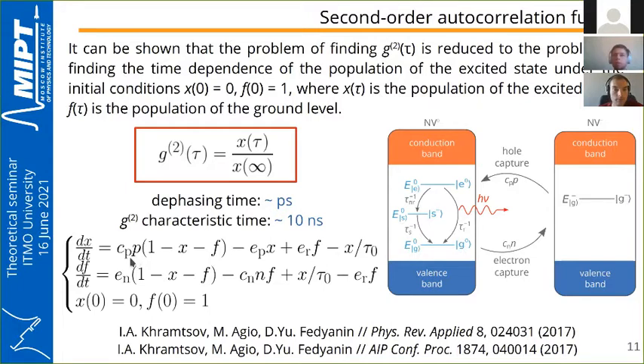We can capture the hole, which is Cp times P times 1 minus X minus F. We can then thermally release the hole from this state. It's proportional to the excited state population.